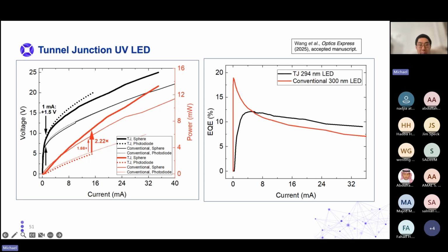So this is the high light extraction efficiency from the small p-GaN islands that we can see here. But with this fully transparent tunnel junction UV LED, it's even better than the p-GaN islands, with an increased factor of 2.22 times over the photodiode bottom side only measurement. And this comes at a not tiny voltage penalty, but not big at all, at just 1.5 volts at 1 milliamp, or 1 amp per centimeter squared, since our devices are 0.1 millimeter squared. And at higher current densities, this voltage penalty is around 2 volts.